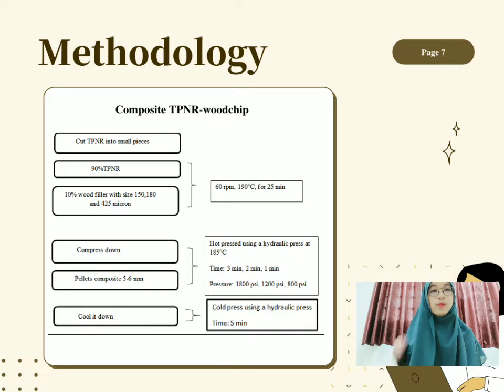Now we will move to how to get the TPNR woodchip composite. First, we cut the TPNR into small pieces, and the composition of the TPNR woodchip composite is 90% TPNR and 10% wood filler. Using the melt blending method, it takes about 25 minutes to get the final result, also at a temperature of 190 degrees Celsius with 60 RPM. After we get the TPNR woodchip composite, we compress it using a hot press machine, which is a hydraulic press at 185 degrees Celsius.